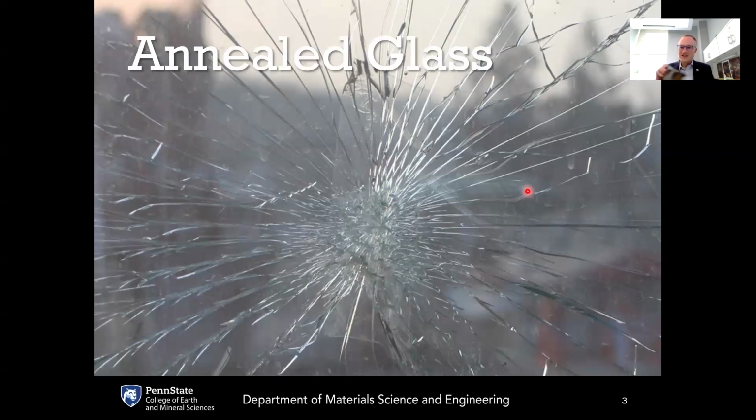For example, there's the glass telescope here that was on the cover of our book, Fundamentals of Inorganic Glasses. This image is actually coming from the Corning Museum of Glass of the first failed attempt at annealing this enormous piece of glass that ended up cracking, and they had to start over again from scratch to do it for an even longer period of time to prevent cracking. And so the annealing process can take any amount of time based on the thickness of the glass in question.